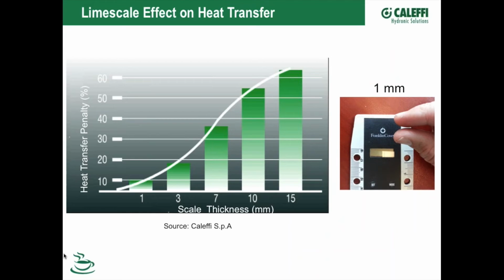Yeah, so you look at that 1 millimeter. That's really not a lot of lime scale buildup. 10%. That's less, as Bob said, less heat going in to the building. More losses. And the other thing to consider is if this energy is not going into the building, typically you're going to see an elevated stack temperature and possible problems there as well.